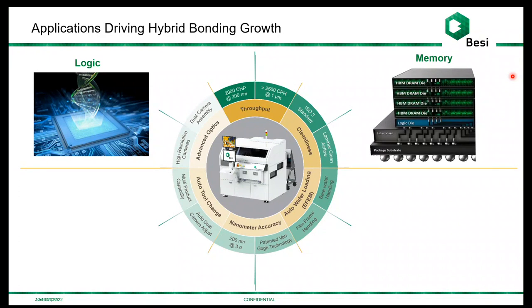And as you go to 16 devices, you simply run out of space because this whole HBM stack has to be at least thinner than the logic device sitting next to it. That's because you need to create a good thermal interface to the logic device and to the memory device. So you can't have a very thick memory device. Therefore, once we go to a 16 die stack, we think just from a height perspective, as well as a thermal performance perspective, we'll need to go to hybrid bonding.